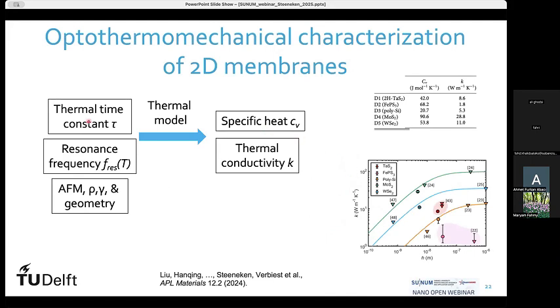And we made a model to use that thermal time constant in combination with the resonance frequency and some AFM measurements to characterize the thermal properties of the membrane. We characterized the specific heat and the thermal conductivity, and we compared our measurements to experimental data from other works. We did that for membranes of different thicknesses and different material properties. Here are the different materials. The circles are our data, and the triangles are literature values. You see that for each of these materials, our circular points are quite well matching the literature data that was there up to then. So this shows that the thermomechanical resonance can also be used as a tool to characterize thermal properties of 2D materials.